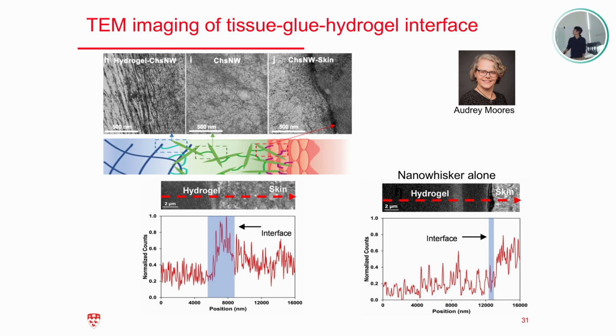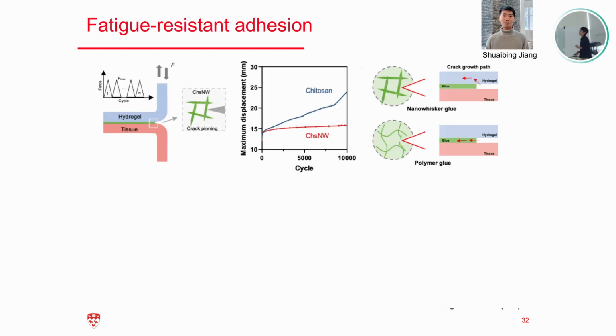So in the case of no ultrasound or no delivery approach, if we use these nanowhiskers alone, as you can see here, we get a very weak adhesion, and also we don't get the penetration of this material into the tissue. And that kind of explains, okay, at least we see what's going on at the interface. And what's most exciting is the nice adhesion performance enabled by this nanowhiskers layer.